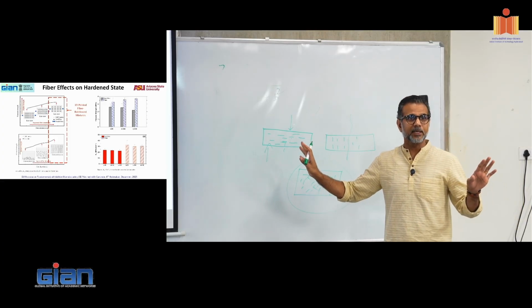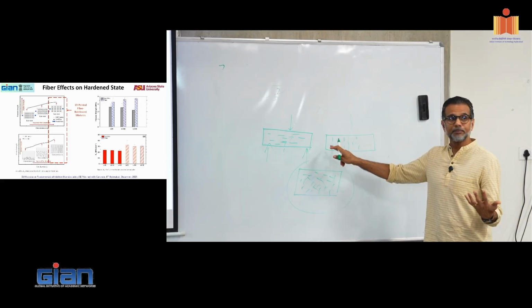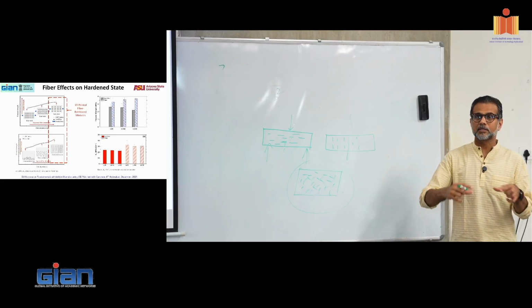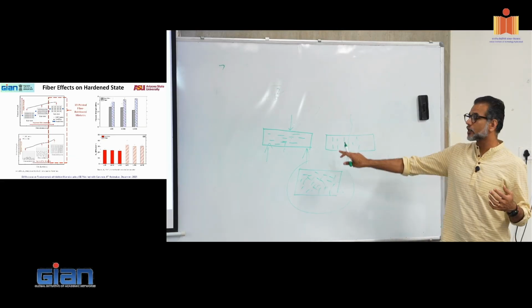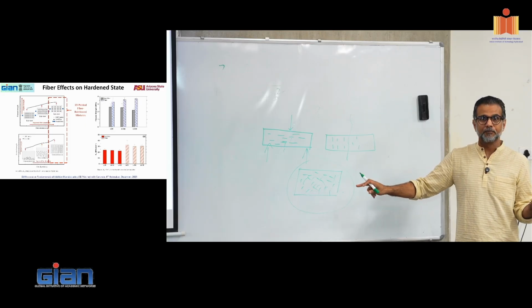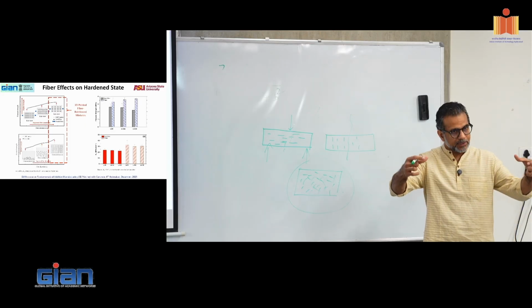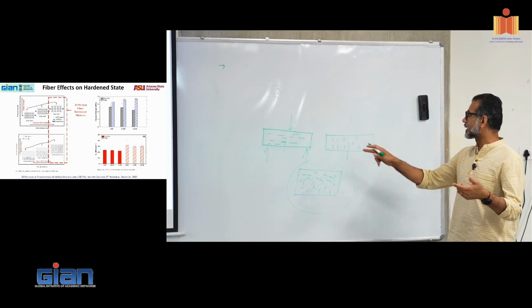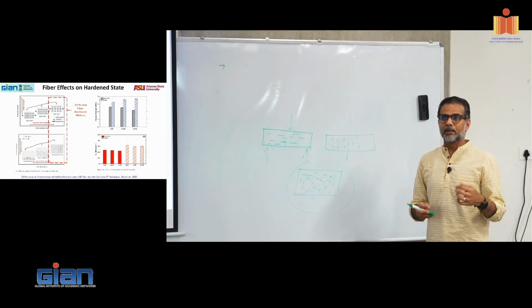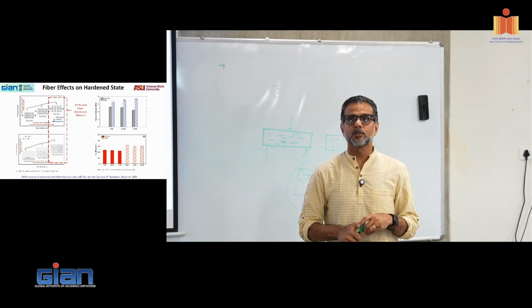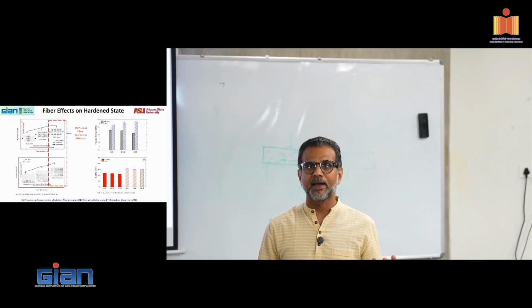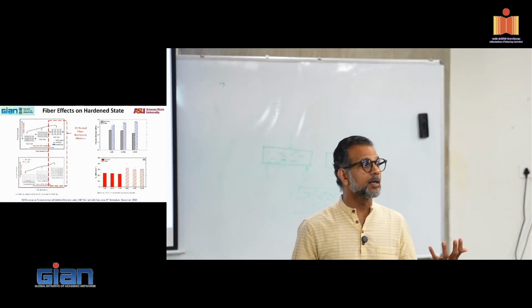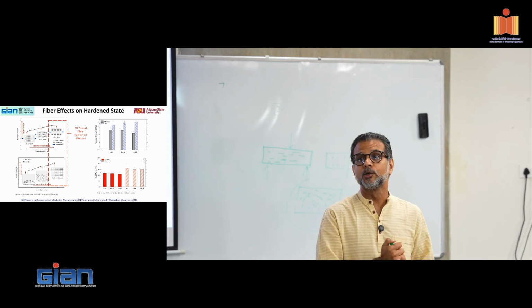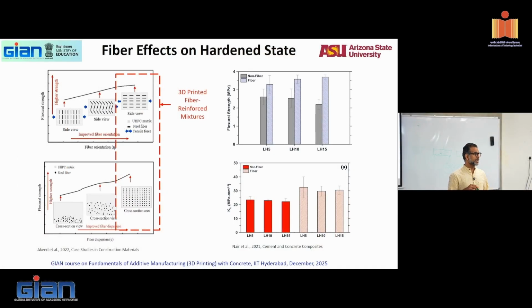So everybody gets the difference, right? Printing direction matters. How you print, what direction you print matters with respect to testing. Now, if you print a slab and cut a piece of beam to test, the direction of testing matters. So when you say that you got so and so flexural strength when you used fibers in your 3D printed mixture, what you have to specify absolutely is what was the direction of testing, because you're dealing with now an anisotropic composite.